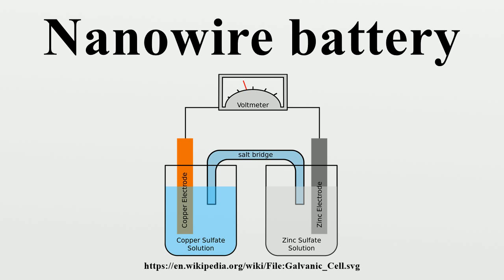Germanium. An anode using germanium nanowire was claimed to have the ability to increase the energy density and cycle durability of lithium-ion batteries. Like silicon, germanium has a high theoretical capacity, expands during charging, and disintegrates after a small number of cycles. However, germanium is 400 times more effective at intercalating lithium than silicon, making it an attractive anode material. The anodes claim to retain capacities of 900 mAh per gram after 1100 cycles, even at discharge rates of 20 to 100 C. This performance was attributed to a restructuring of the nanowires that occurs within the first 100 cycles to form a mechanically robust, continuously porous network.